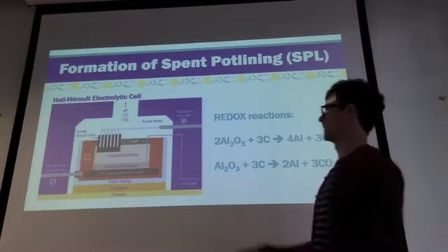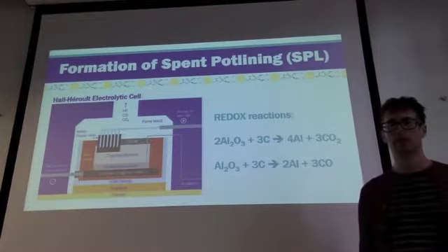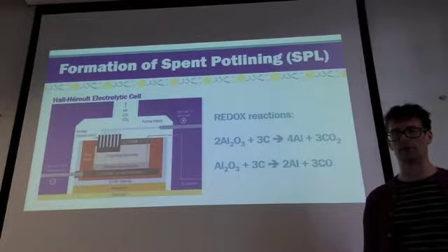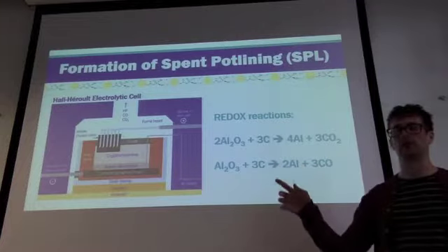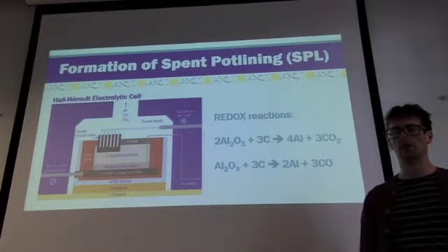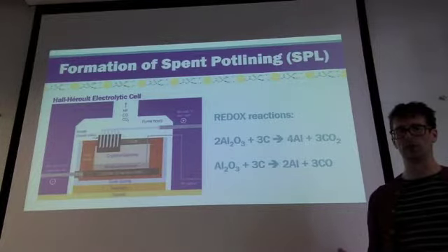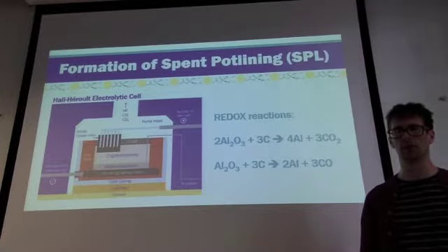What we're going to zone in on though is this cathodic cell lining material here. Now the cathode bar is not in itself consumed in the electrolysis reaction. It does however become degraded over a period of time due to contamination seeping into it from these very harsh reaction conditions above. And when the contamination proceeds to such an extent that the quality of the aluminium metal produced begins to suffer, the cell is decommissioned and drained, and all of the contaminated cell lining material is excavated, becoming spent pot lining.